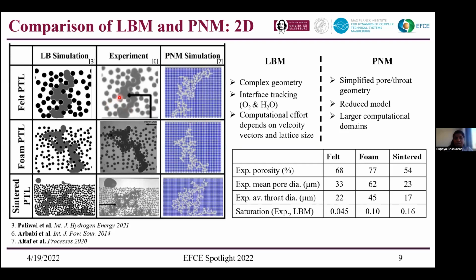So now how do we compare our LBM and PNM in 2D. So here I have considered 3 different PTL structures, that is the felt, foam and sintered PTL. These have approximately 68, 77 and 54 percent porosities respectively, and a mean pore diameter of 33, 62 and 23, and also a throat diameter of 22, 45 and 17. As I said before, LBM can actually incorporate the real geometry. You can see from the experiment, we could actually derive the exact geometry and apply our Lattice-Boltzmann model. And we also got a similar invasion trend of oxygen comparing the experiment and LBM.